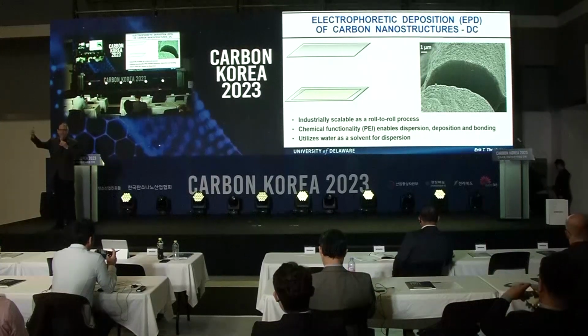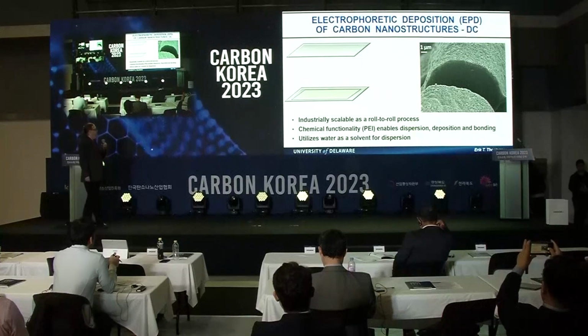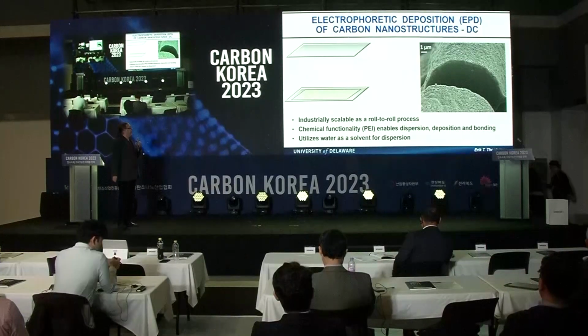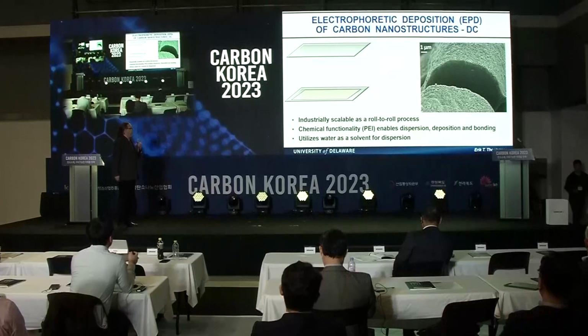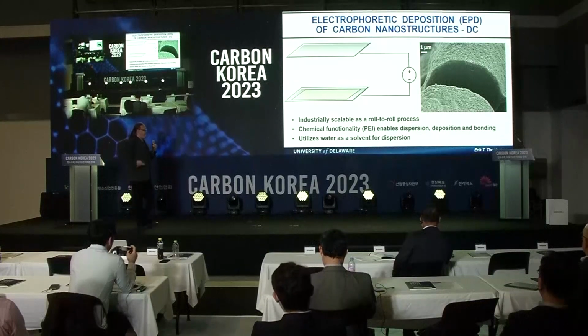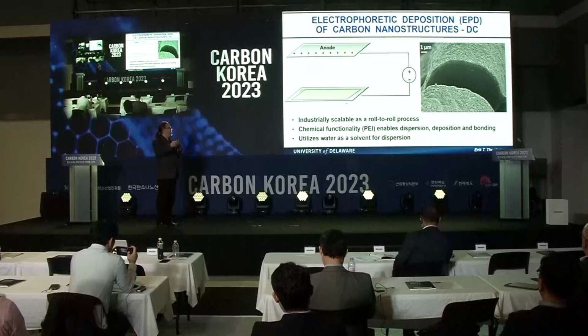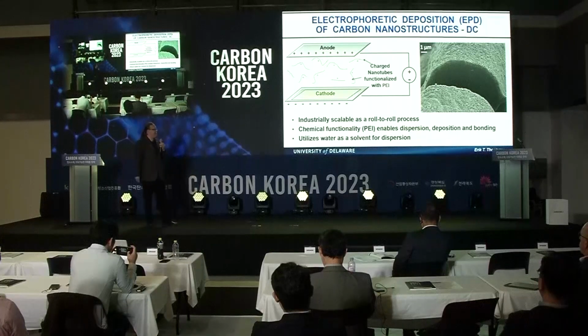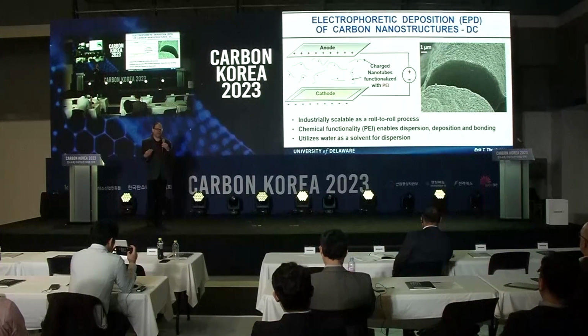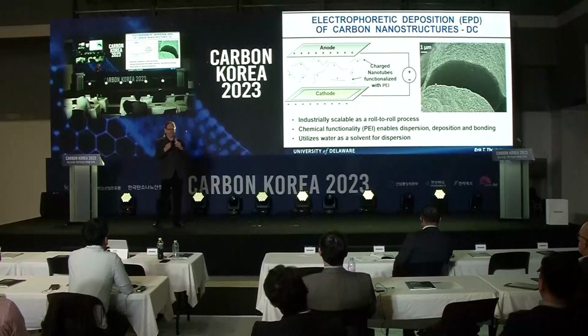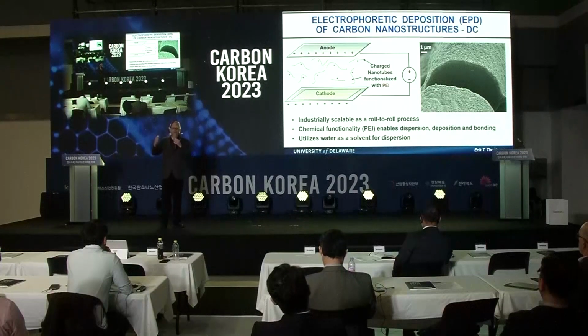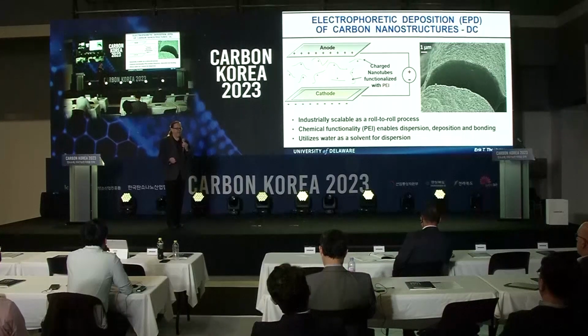So what we do is we create a dispersion of nanoparticles, in this case carbon nanotubes. We disperse them in water, and we chemically functionalize them, in this case, with a cationic polymer. And when we lower the pH, they protonate. And that does a couple of things. The positive charge stabilizes the dispersion, so the charges will repel each other, but that gives it mobility. So what we can do is use that electric field to deposit the carbon nanotubes.